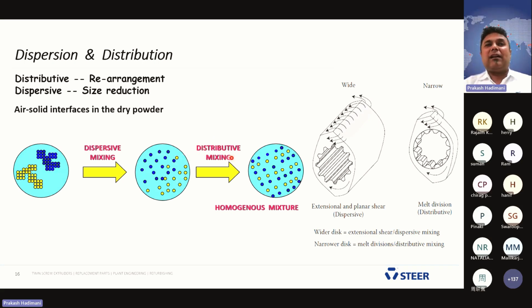Distributing these two colors to get a homogeneous mixing, we call a distributive mixing, because your polymer and your pigment have to be distributed evenly in the polymer. In this form, that is called homogeneous mixing. I have put a wider kneading block here. This is a screw design like a kneading block. Sometimes when you use a wider kneading block, it gives better dispersion. It has a tendency to break the particles smaller and smaller, that we call dispersion. And the thin kneading block, we call a narrow thin kneading, a distributive mixing.